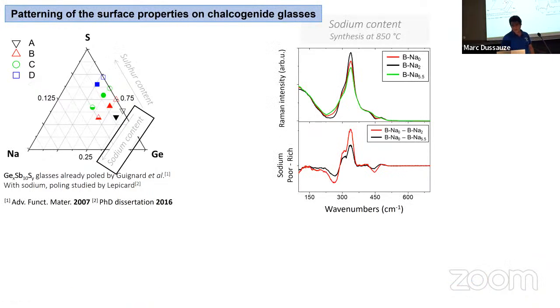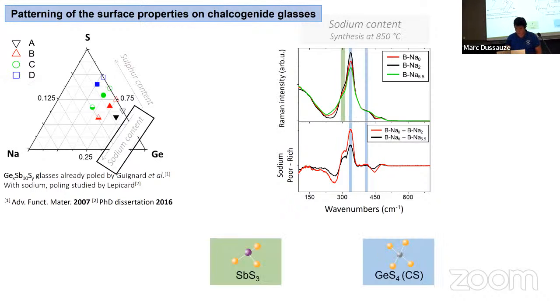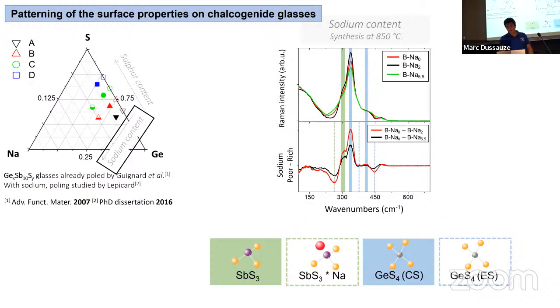If you change now the sodium content, you will see that the structural changes are less pronounced. Sorry, you still affect a little bit the germanate networks and quite a lot the antimony environment. But as you can see in this top figure, the Raman spectra are not so much modified.